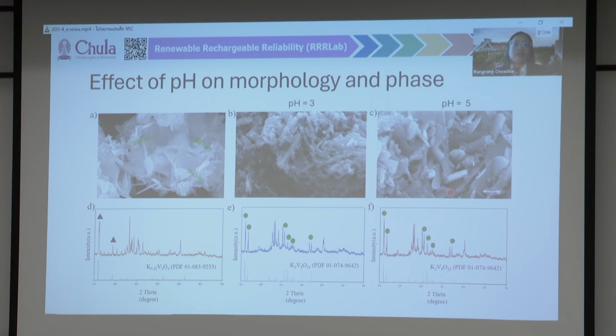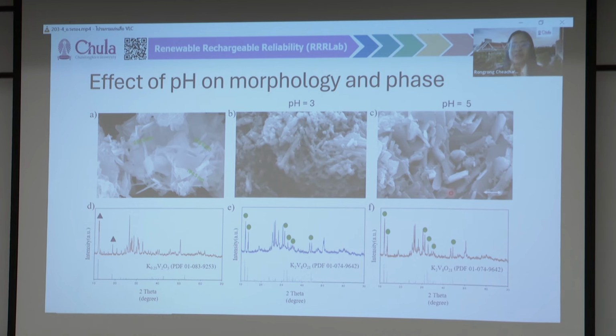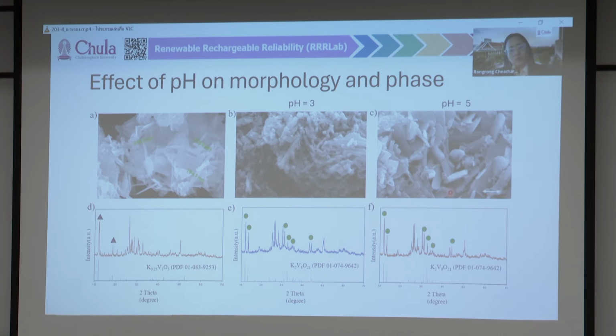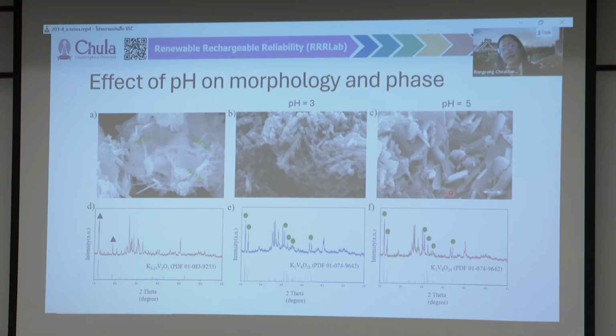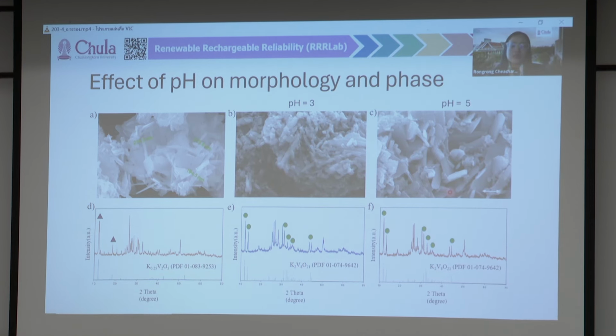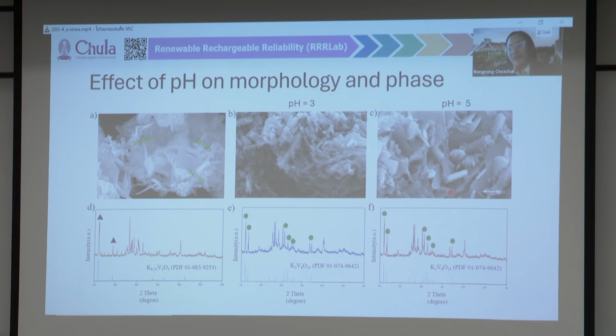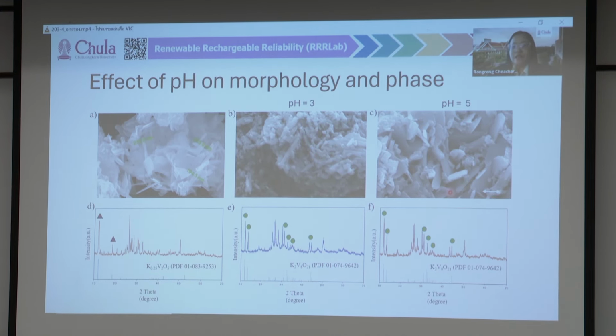We just put everything as is and do the synthesis. This one seems to give us quite a good nanowire shape, but it's quite random. But when we do a pH of 3 or 5, the size seems to increase a little bit as we increase the pH a little bit more. But it's interesting to notice that the phase that we got for pH 3 and 5 are quite similar. The only difference is the morphology.